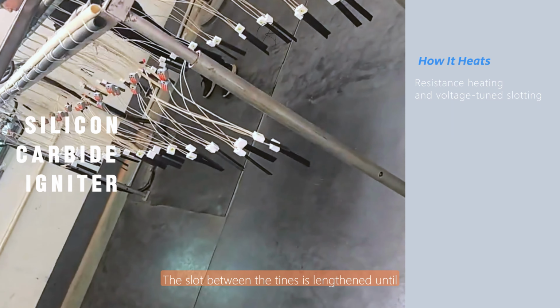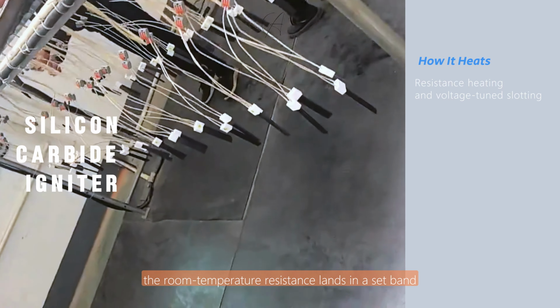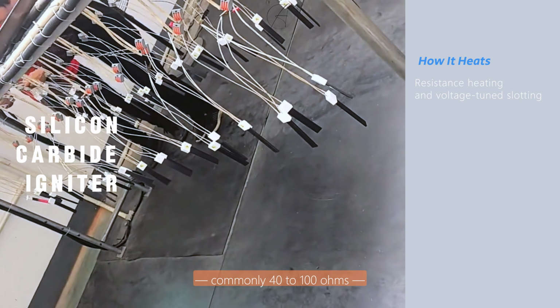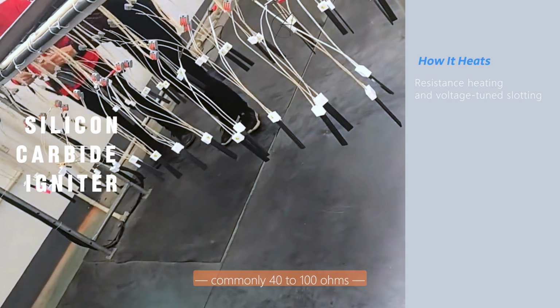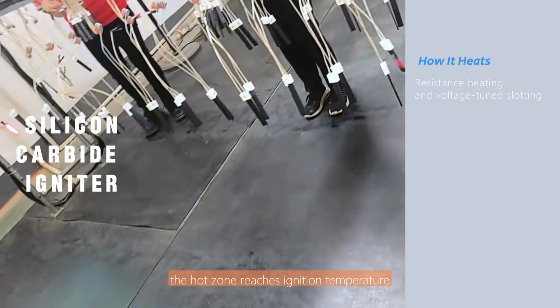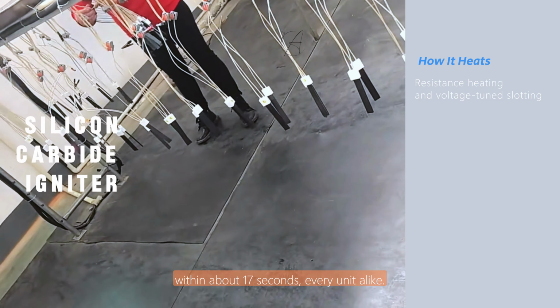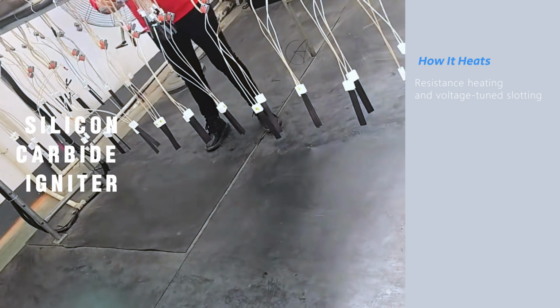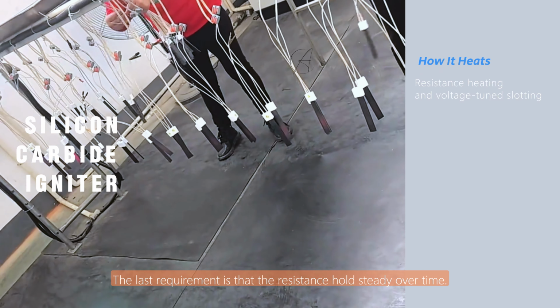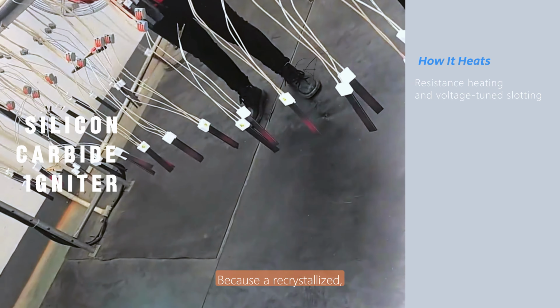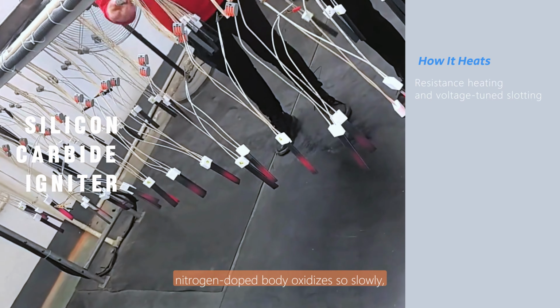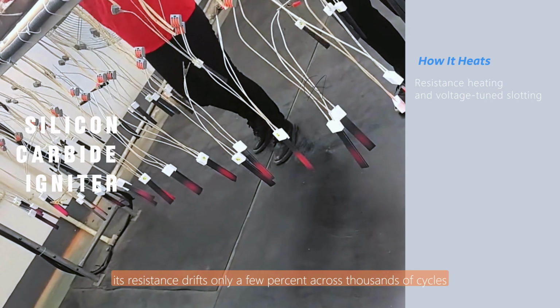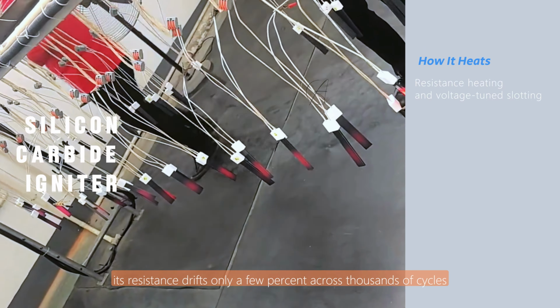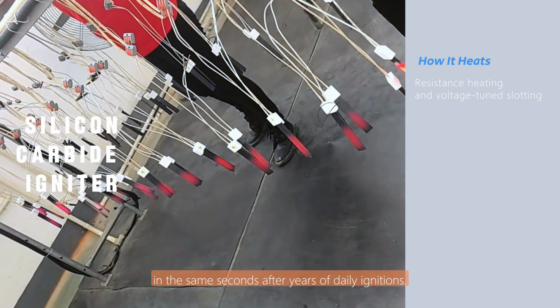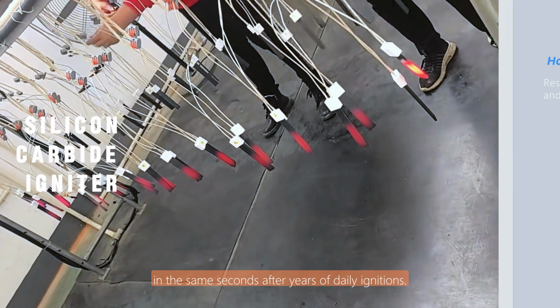The slot between the tines is lengthened until the room temperature resistance lands in a set band, commonly 40 to 100 ohms. So that at line voltage the hot zone reaches ignition temperature within about 17 seconds, every unit alike. The last requirement is that the resistance holds steady over time. Because a recrystallized, nitrogen-doped body oxidizes so slowly, its resistance drifts only a few percent across thousands of cycles, so the same element still reaches temperature in the same seconds after years of daily ignitions.